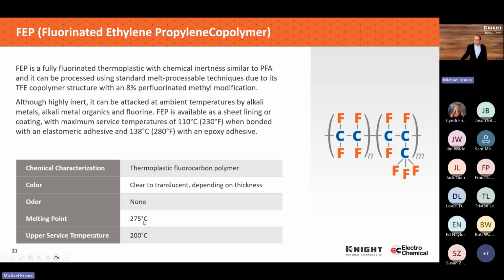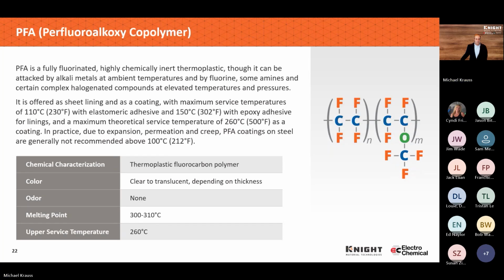And again, when we talk about the upper surface use on FEP by itself, we're showing here about 200 degrees Celsius. From a lining perspective, we're considerably lower at about 110 degrees from a lining application due to the adhesive systems that are used. Therefore, in a lot of cases, there's no significant benefit to use PFA, and you can actually save money and have a more cost-effective solution.